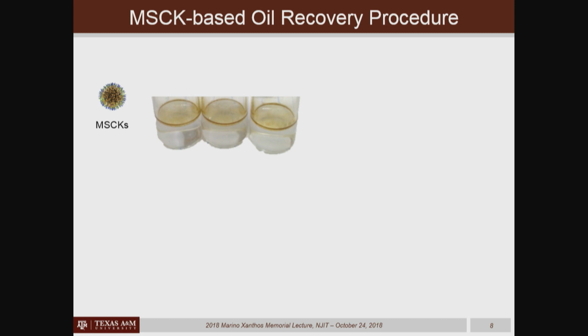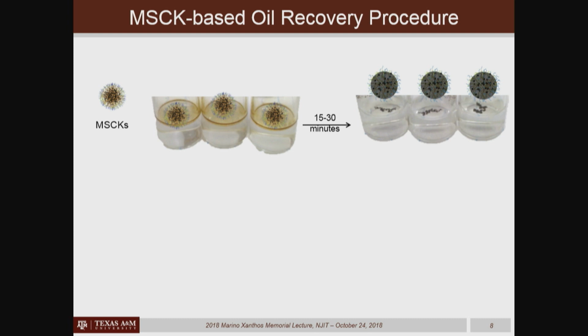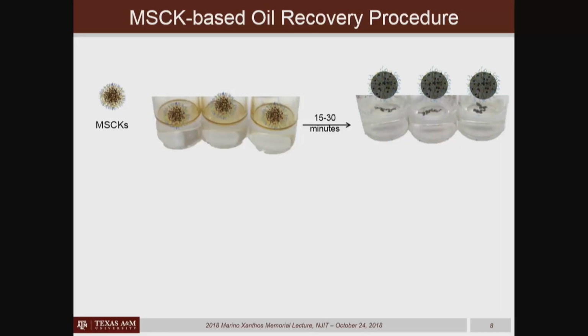And when Adriana tested how well they could perform in collecting crude oil, she conducted a series of experiments. And what's shown here is a photographic image of 3 vials, each containing water with crude oil floating on the surface. And then there's just going to be a cartoon representation of her administering the nanoparticles. But after a period of just minutes, when you see the image of those vials, now the crude oil has all been collected within those nanoparticles. The nanoparticles start out as kind of a light brown color, and you can see here these are quite dark in color. So the oil-filled particles darken in color. They also then float and aggregate together. And so you can see these aggregated floating islands of particles on the surface of the water.